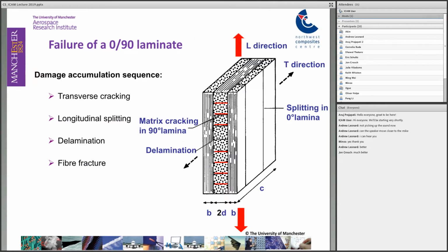And here we can see how damage evolves in a composite multi-layered construction. Here we have a cross-ply 0/90 laminate, and we can see how damage initiates in the form of matrix cracking in the 90-degree layer. At the tip of the crack, you develop now a three-dimensional stress field where maybe it doesn't have enough energy to break the neighboring plies, the fibers in the zero ply, but they're high enough to introduce delamination, separation of neighboring plies. And if that laminate is loaded under biaxial loading, then you're going to see that matrix cracking or splitting starts to propagate in the zero layer.